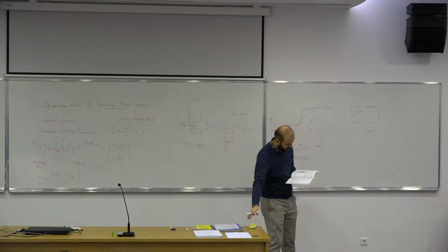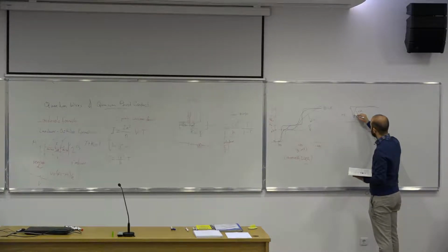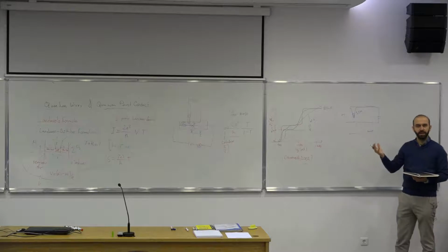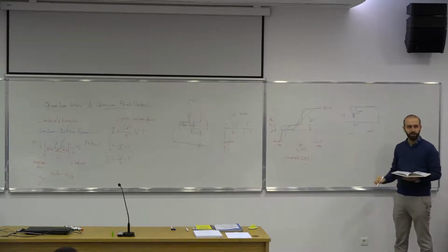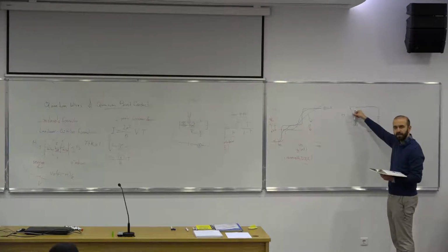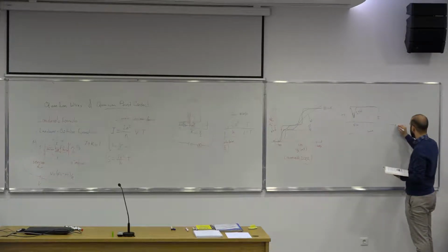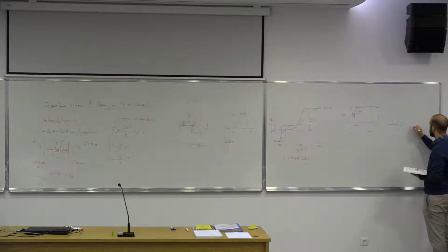What they do is, on the tip of an STM, they coat it with a metal, okay? They put, I don't know, something like gold, and their substrate is also gold. Then they lower down the STM tip and make a physical contact with the gold substrate. Then they start pulling it apart. Now this is the contact case, and as you start pulling it apart, this junction here gets smaller and smaller, so it narrows down as you pull it further away, okay?